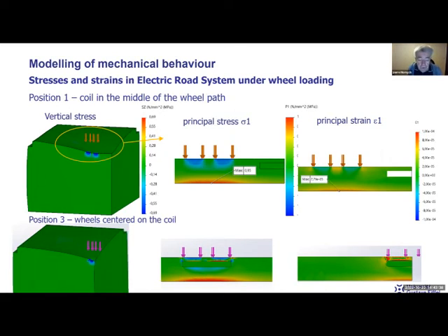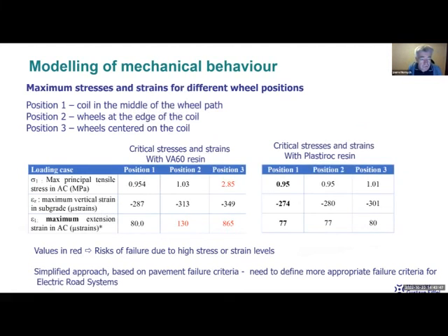So in fact, the number of load applications in this situation will be reduced in comparison with the number of passing trucks. And so we tried with this mechanical model to predict the maximum stresses and strains for different wheel positions. For position 1, where the coils are in the middle of the wheel path, position 2, where the wheels are at the edge of the coil, and position 3, where the wheels are centered on the coil. And we calculated the critical stresses, so the maximum principal stress sigma 1, the maximum vertical strain epsilon z, and the maximum tensile strain at the bottom of the asphalt layers epsilon 1.